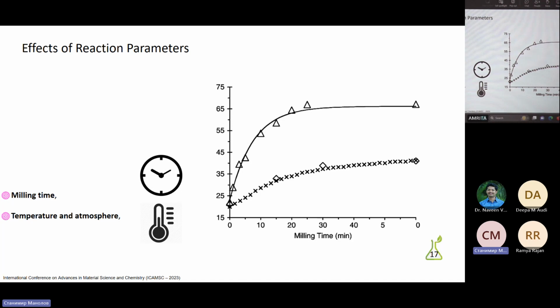The revolution speed must be optimized to obtain the desired product with high yields and quality. As a result of more powerful mixing and the increasing number of collisions, as the revolution speed increases and the energy input increases, higher yields and better substrate conversion can be obtained. High speeds may cause byproduct formation, or the increasing temperature may cause the decomposition of the metastable phases. The temperature increase can be useful if diffusion is required for powder alloying. The lower revolution speed causes less energy consumption, lower cost, and is more energy efficient.